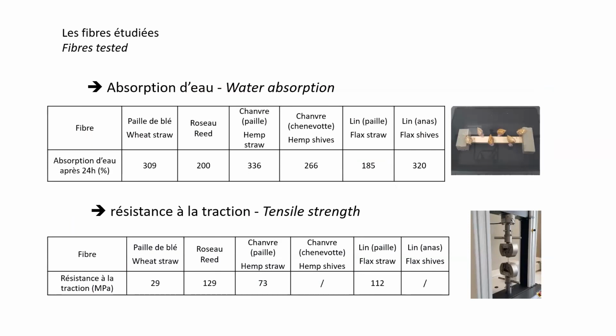Their capacity of water absorption. So this could obviously have an impact on rather viscous mixes or plastic mixes like cob. So the more you have a fiber that absorbs water, the more you need water, and therefore this can make drying times longer. And there was also this question of tensile strength, which could also play a key role in these mechanical properties for the load-bearing cob especially. So we realized that the fibers that gave us the best results for water absorption were reed and flax straw.